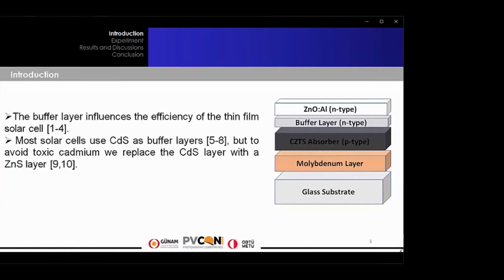In this presentation, we focus on the buffer layer, which is located between the absorber layer and the transparent conductive oxide layer. This layer influences considerably the performance of the thin film solar cell. Generally, most solar cells use CdS as the buffer layer, but to avoid toxic cadmium, we replace the CdS layer with a ZnS layer. In this work, we are interested in the elaboration of zinc sulfide films and studied the effect of the solvent and temperature on the optical, morphological, and structural properties of our layer, which has been prepared by the Mist CVD technique.